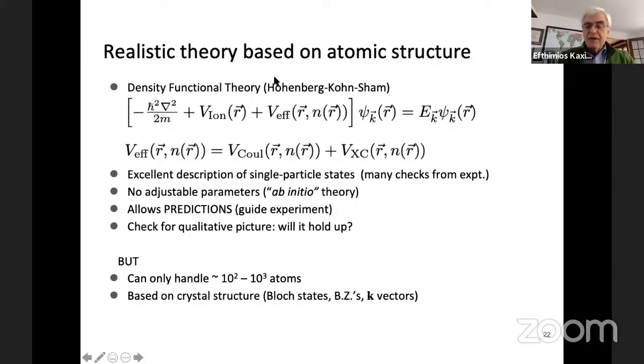So we made it our goal to produce a realistic theory based on the atomic structure. What I showed you a moment ago was a sort of a qualitative picture. So we wanted to put together a quantitative picture. So this relies on a very elaborate set of equations called the density functional theory. Nihad mentioned in his introduction this kind of approach. It's called an ab initio theory because it contains no empirical parameters, and it can really give us a very detailed and realistic description of the system.